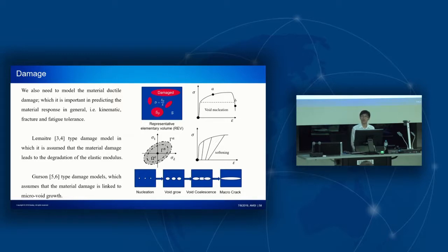Finally, is the material ductile damage. There are two most common ductile damage models that have been widely applied these days. One is called the Lemaitre ductile damage model, which directly models the degradation of the material elastic modulus. When the elastic modulus goes down to zero, then we say a macro crack happens. And the other approach is called the Gurson ductile damage model, which directly models the material macro void growth. So it models the damage of material in four stages. Firstly is the nucleation of the macro void, and then the void will grow. Eventually, they will connect and finally form the macro crack.